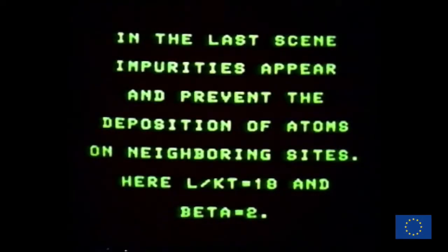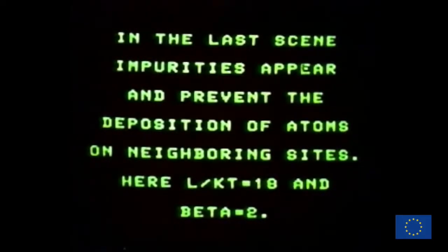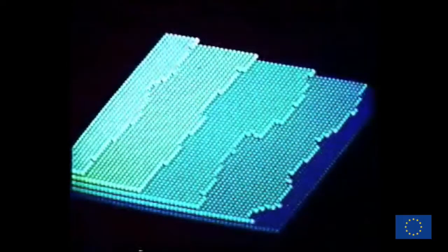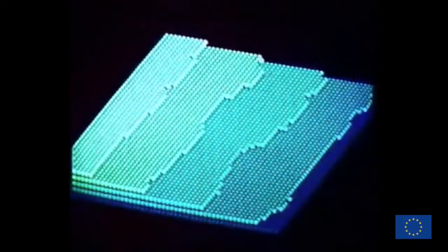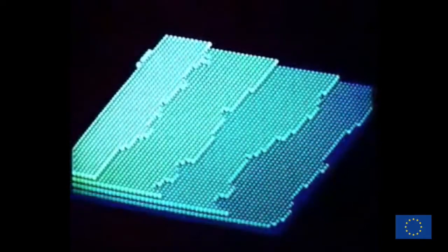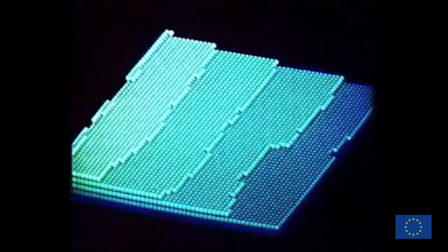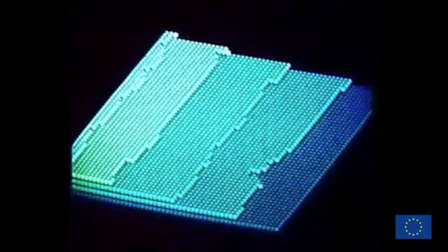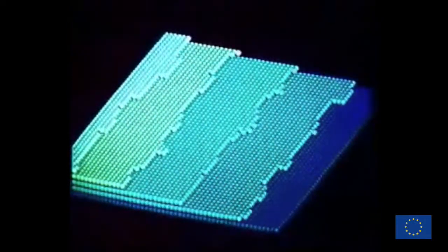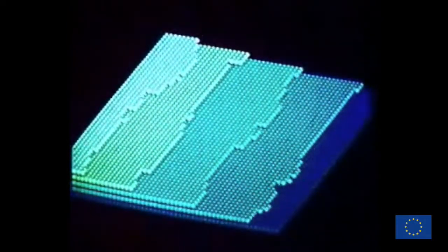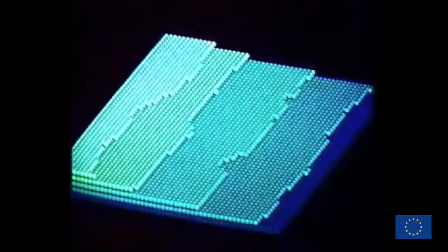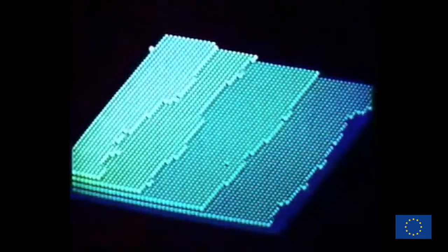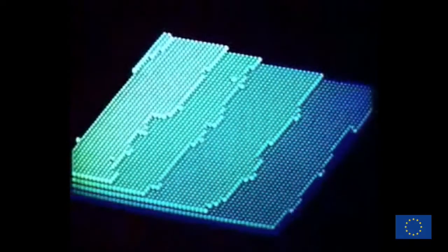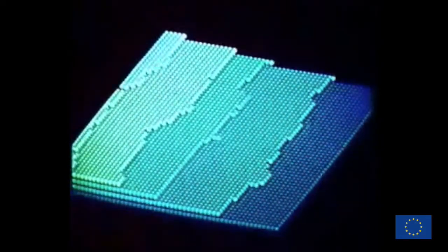That's why we need to wait for the second movie, where first I want to show you Stepflow. Stepflow is in fact the regime that crystal growers prefer to maintain smooth surfaces, and it is shown here. It is the case where you have equidistant steps on your surface that then grow by moving from the left to the right. And the advantage of this regime is that you can continue it forever and forever while maintaining a perfect surface morphology, being the best case that you can have, one atomic step.